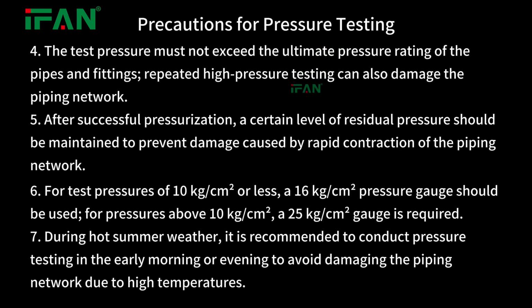Repeated high-pressure testing can also damage the piping network. 5. After successful pressurization, a certain level of residual pressure should be maintained to prevent damage caused by rapid contraction of the piping network. 6. For test pressures of 10 kg per square centimeter or less, a 16 kg per square centimeter pressure gauge should be used. For pressures above 10 kg per square centimeter, a 25 kg per square centimeter gauge is required. 7. During hot summer weather, it is recommended to conduct pressure testing in the early morning or evening to avoid damaging the piping network due to high temperatures.